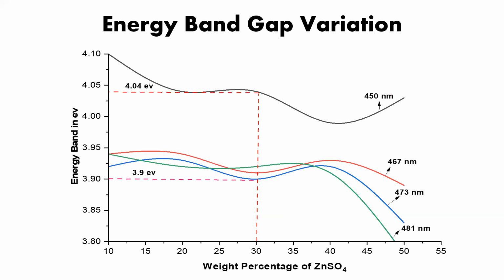This energy band calculation, again on the basis of the excitation energy data, I analyzed by some mathematical modeling using very fundamental theoretical calculations. On the basis of that, I found that as we vary the excitation value, the energy band gap shifted. So I was interested to say that band gap tuning is possible with PVP under different excitation, because 4.04 electron volt is reduced to 3.9 electron volt. So it's a marginally good variation of energy band gap.